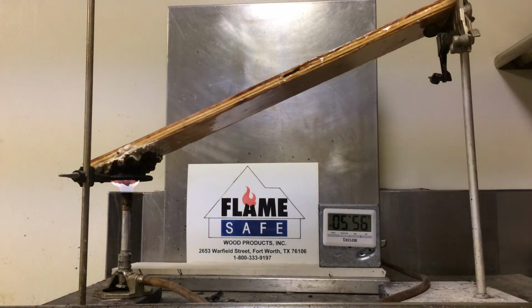The test on this product was conformed and adapted by FlameSafe, and the results were indicative of the test performed at Southwest Research Institute on fire retardant plywood coating. The Fire Poly FP75E test at the Southwest Research Institute showed a flame spread index of less than 5, which correlates almost exactly to the ASTM D3806 test that you are watching at the present time.